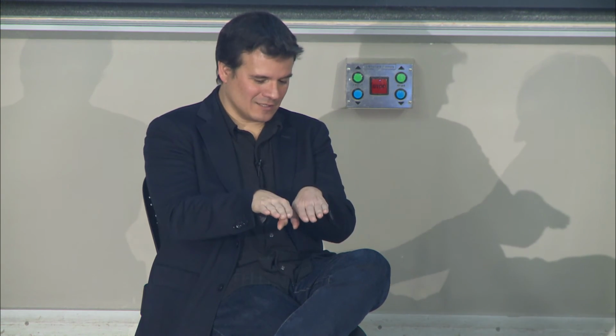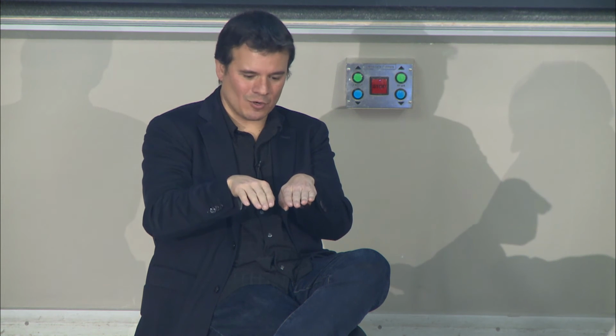Well, in fact, the thing that I described is how we originally did it, as of a couple of years ago. A couple of years ago, one of my students thought that this ripping, this tearing, is actually very violent and it creates a lot of strain at the interface. So what we did is we brought a laser and we just, with a laser, cut the graphene into pieces cleanly, without any strain. And now we can pick one separately and put it on top of the other without that ripping apart. So we're making small improvements already in the process. And of course, laser cutting is much easier to implement than tearing.